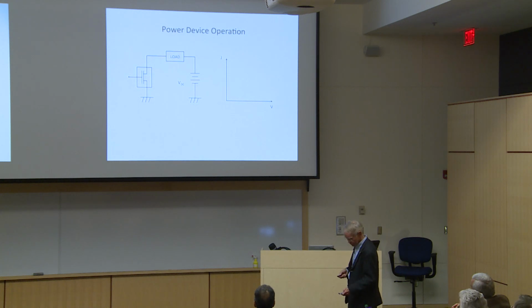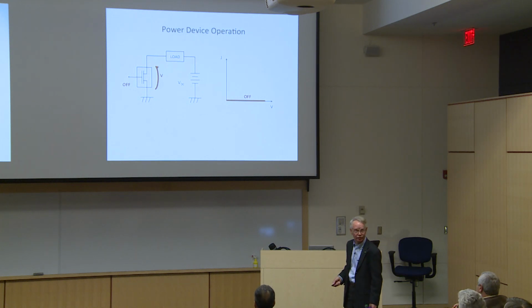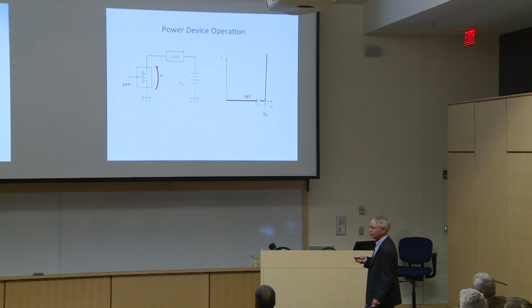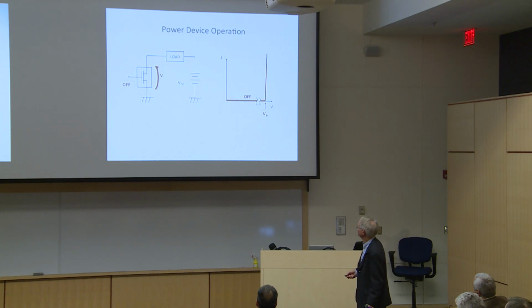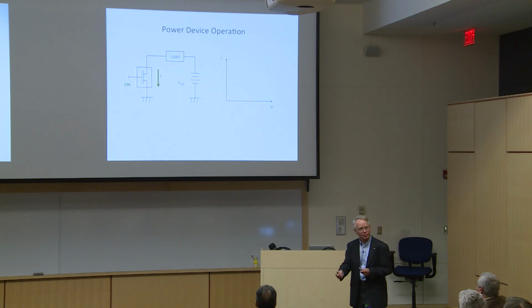So when the switch is turned off, we want to block. We don't want to have any current, and we want this to sustain a high voltage. And so the IV characteristics in the off state should look like that. Essentially no current. And as we go to high enough voltages, eventually the device will break down and we'll get uncontrolled current. So we need to stop short of this blocking voltage. That's one of our parameters. When we turn the device on, we want to have a large current and almost no voltage drop. We want it to be a dead short.